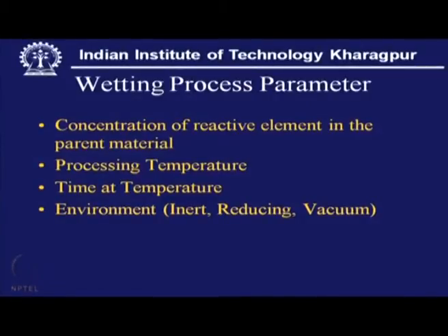So, here we see the wetting process parameters. It is actually the concentration of the reactive element in the parent material, processing temperature, time at temperature and environment.